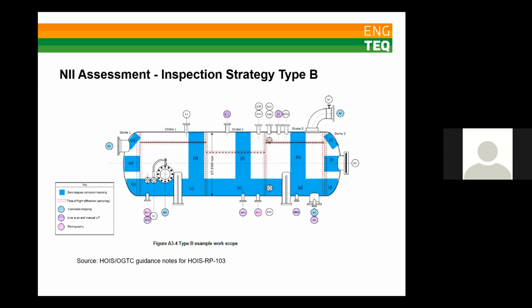So this is a typical example of a type B inspection, again taken from the guidance notes for the recommended practice. And coverage in this case is focused on the areas where degradation is expected or predicted to happen. In this case, you can see that this will be the bottom of the vessel, so you might expect to see a liquid layer here, and possibly also solids collecting. And then the rest of the vessel is subject to a sampling inspection with coverage spread throughout the vessel.